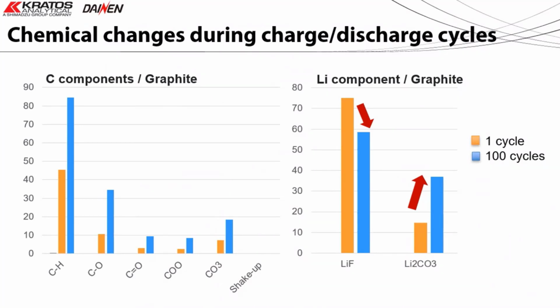So the literature suggests that the reduction of the solvent, dimethyl carbonate, results in generation of lithium methyl carbonate, lithium methoxide, carbon monoxide, and methane. So there's some very complex chemistry going on here, but this is where we're assigning these chemistries.